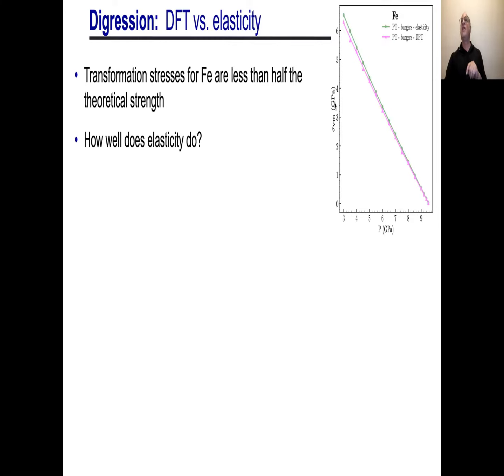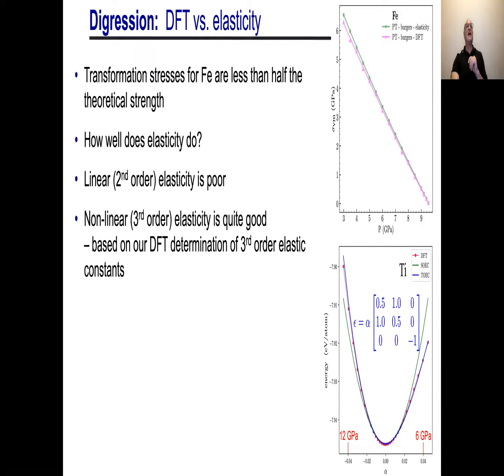Okay, so this is now the pressure for the transformation, and that's the shear stress for the transformation. Down here, the material iron will be BCC. Up here, it would be hexagonal, HCP. The green curve here is what I get from third order elasticity. The magenta curve there is what you get from DFT. Now, I just told you elasticity, no matter how high order, is not going to work very well. Well, that's true if you're near the theoretical strength, but this is at about half the theoretical strength. And actually, third order elasticity does a pretty decent job. Second order elasticity is really not that good. So normal linear elasticity is not that good.